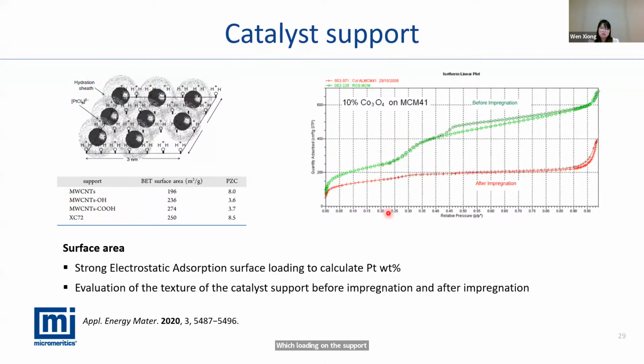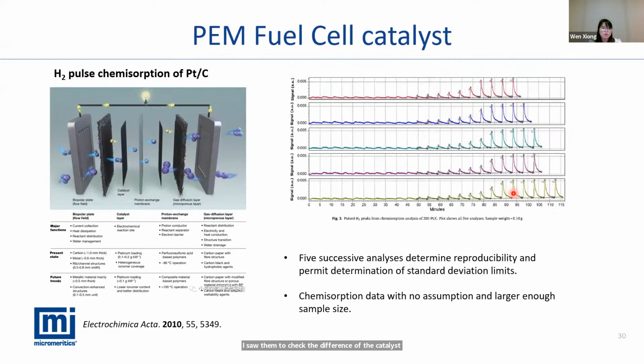The figure on the right shows the texture difference. We can see two different isotherms, before the precursor impregnation and after the precursor impregnation. This is by using our physisorption gas adsorption isotherm to check the difference of the catalyst support. The second example is using hydrogen pulse chemisorption. Actually, it's oxygen pretreatment and hydrogen pulse chemisorption by our AutoChem 2920 on a carbon-supported platinum catalyst.